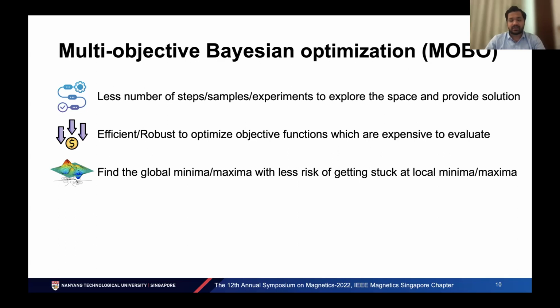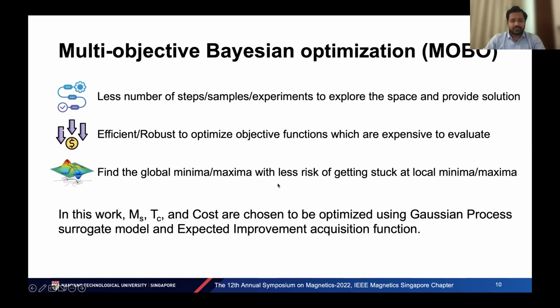Second, it is also very efficient at optimizing objective functions which are very expensive to evaluate. In our case, using the multi-property model, which is the extra trees model, it's very difficult to optimize for such a huge space. Next, it also helps us find the global maxima or minima with less risk of getting stuck at local maxima or minima, which is the case in the majority of the optimization algorithms available. Now, as I said, the inputs were only compositions. So we chose only composition dependent properties, which are MS, TC, and cost for optimization. In the Bayesian optimization, we used a Gaussian process as the surrogate model and expected improvement as the acquisition function.